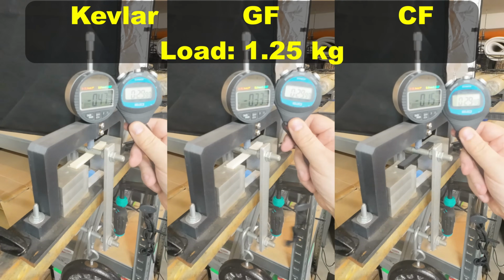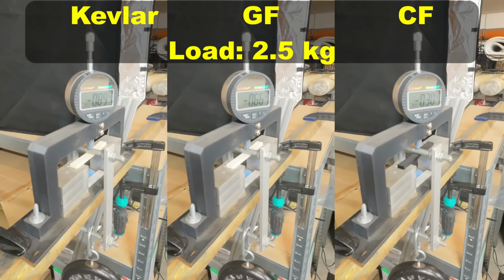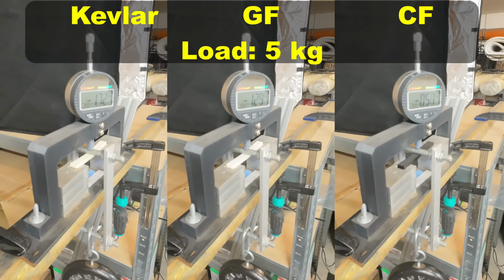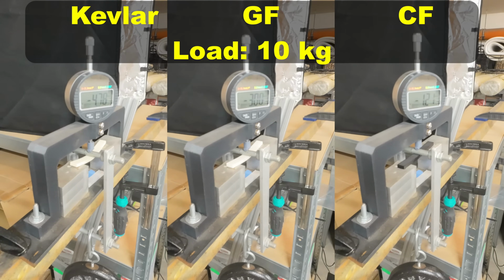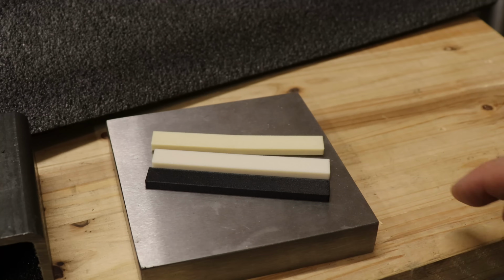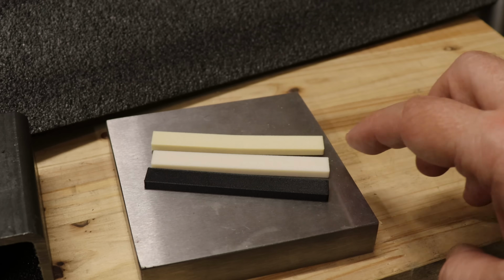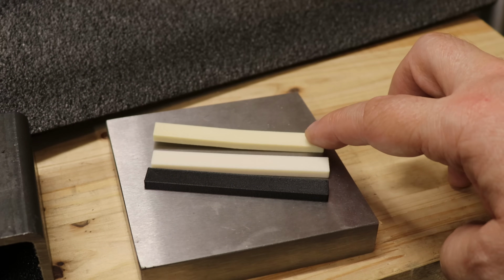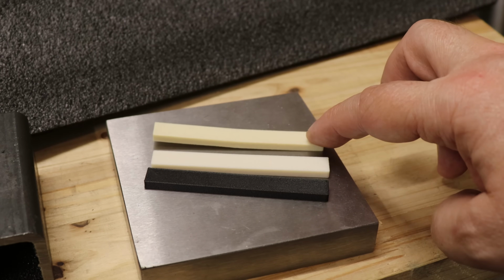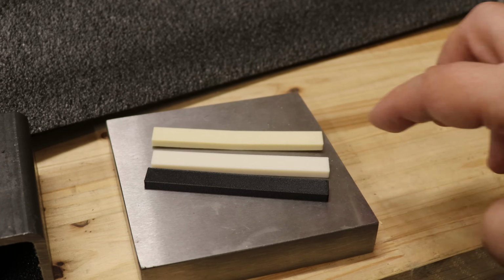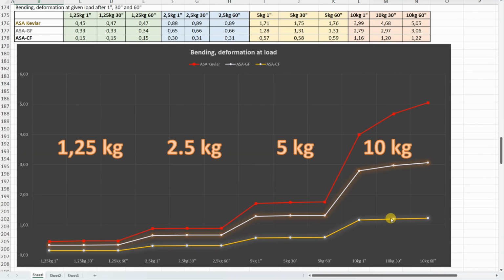3-point bending test. The distance between supports is 50 mm, and these loads are placed one by one, and I am recording the deformation after 1, 30 and 60 seconds. And currently you can see the deformation under 10 kilograms. The permanent deformation is very minimal on carbon and glass fibers. On Kevlar, during the test it had a huge deformation, but now the permanent deformation is visible but much smaller. In this case the carbon fiber version is quite strong, very minimal deformation, even under 10 kilograms. And the Kevlar, quite weak. Look at this big deformation under 10 kilograms during that 1 minute. And the glass fiber version is somewhere between.